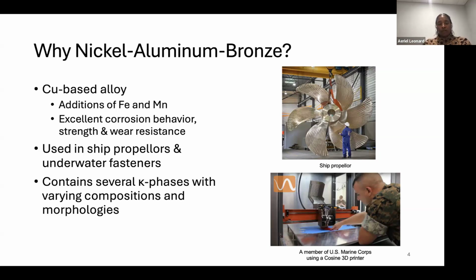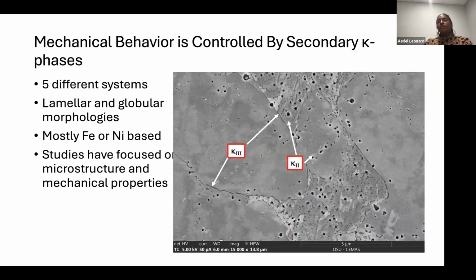And some of the most important phases are these kappa phases. In general, there are these secondary kappa phases, about 5 different systems. They can vary in morphology. They can be lamellar, globular, or spherical. They're mostly iron or nickel based. And we'll talk a little bit about them going forward.